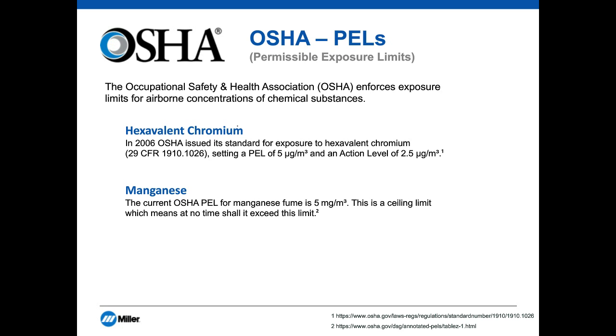About 7 years ago, OSHA came out with their first new standard in terms of industrial hygiene in quite a while, and that had to do with hexavalent chromium. The hexavalent chromium standard actually touches on two distinct processes: plating operations using chromic acid, but it also covers welding on stainless steel. Stainless steel contains chromium in its natural or trivalent state, +3. When you heat chromium-3 up to high temperatures, such as when welding, it changes into chromium +6, otherwise known as hexavalent chromium. Hexavalent chromium is extremely corrosive and can affect lung tissue.